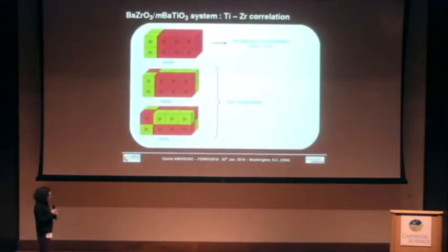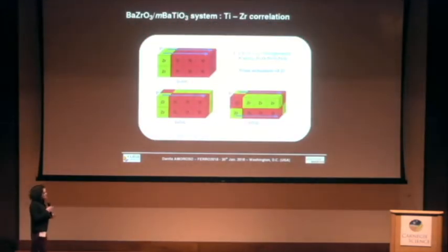To answer this question, we built specific supercells where we preserved the local titanium-oxygen chains by substituting one titanium atom with one zirconium. We also took care to distinguish the effect of a decreasing zirconium concentration, like in this superlattice case, from the effectively local effect due to this specific pattern of atomic arrangement. And the answer to the previous question is yes.